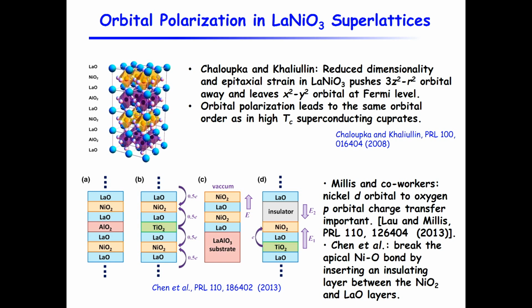For example, people pointed out that you do have charge transfer between the nickel d orbital and the oxygen p orbital that makes this orbital polarization much less than what the original theory predicts. But then there are people suggesting different kinds of heterostructures. For example, put some insulator here to prevent this charge transfer, in the hope that you might be able to create an artificial high TC superconductor. Of course, if you want to do this, you would have to have the capability of growing these materials at the atomic layer by atomic layer level.